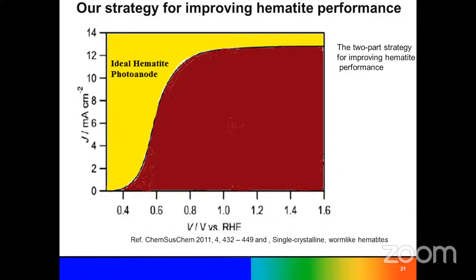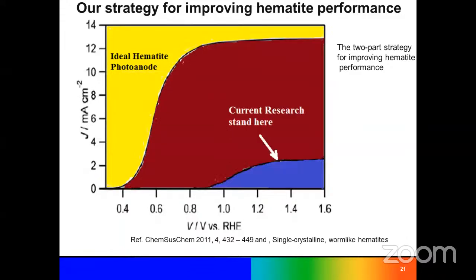So for this commercialization, if you see the curve, an ideal hematite photoanode can reach around 12 milliampere per centimeter square current density, and the minimum voltage required is 0.4. But still now, in the current state, we are standing here, where the current density is around 2 milliampere per centimeter square, and the voltage required is still around 1 volt. So our target is to improve this current density as well as the minimum required voltage.